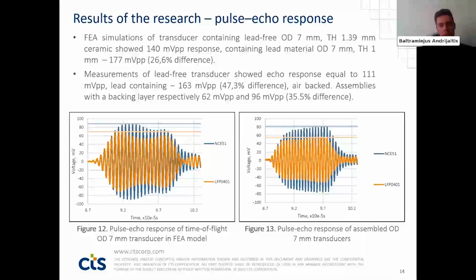Finite element analysis showed around 27% difference between materials in performance, and measurements of the ensemble reached even approximately 50% difference while comparing them without a backing layer. However, lead-free samples with a backing layer showed only 36% lower performance than lead-containing, and this value was considered as the final one to compare them. The model in general is quite matching. The differences between simulated and assembled transducers could come from previously mentioned reasons.